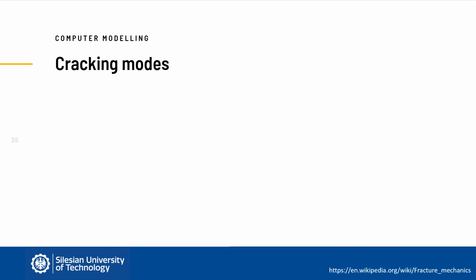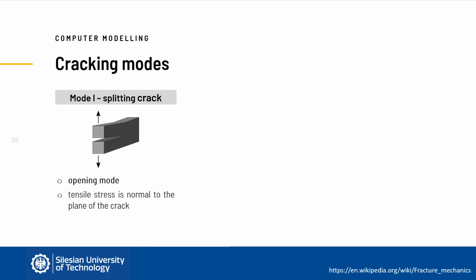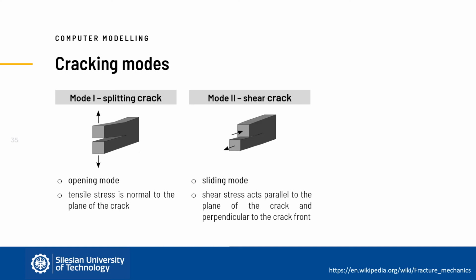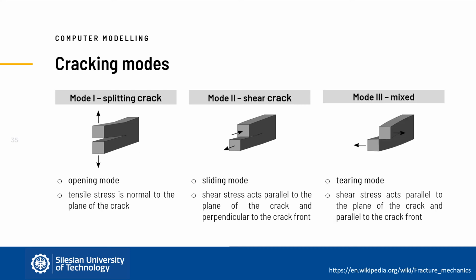In general, there are three modes of cracks. Opening mode, in which a splitting crack is formed. This is a commonly known crack which is formed under tension. When concrete fails under compression, such as for example in a uniaxial compression test, a sliding mode of fracture occurs with a shear crack. Finally, a mixed mode of the two can occur, which leads to a tearing crack.